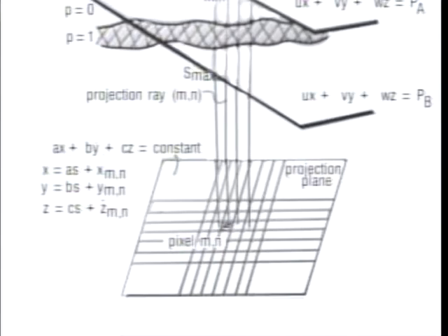And then we can create on the computer screen a grayscale image that simulates what would happen if a perfect substance with exactly this constant mean curvature idealized interface were to be subjected to a perfect transmission electron microscope experiment. We also model in a little bit of the optics of the situation. Now one can make comparisons between the simulated projections, grayscale images, and the ones produced by the electron microscope.